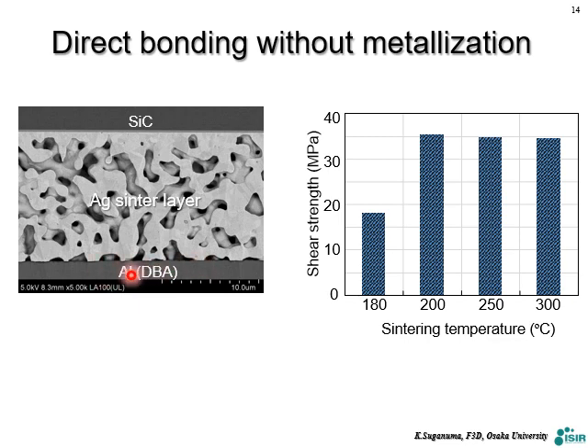Usually, for DBA, we have to make nickel plating on it for soldering. Otherwise, we cannot make joints. But without any metallization, we can make direct bonding with silver sinter materials. And the shear strength, even at 180 degrees C, we can get almost 20. This is not so bad.